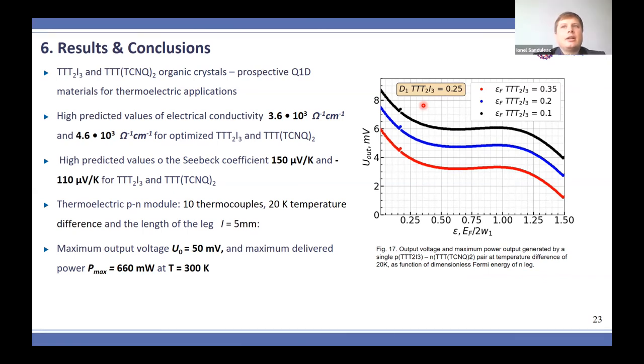Yes, thank you. For practical applications, we are aiming for low temperature gradients, because the structure is organic with iodine inclusions in the P-type, and the iodine can easily evaporate from the structure. But for low temperature gradients, I mean near room temperature, the structure is very stable. My PhD supervisor, Professor Kassian, kept such a crystal in his house for 20 years. And he repeated the experimental measurement after 20 years, and the results were very good, better than the initial ones. So there is a temporal annealing of the properties, because the structure is rearranging over time.